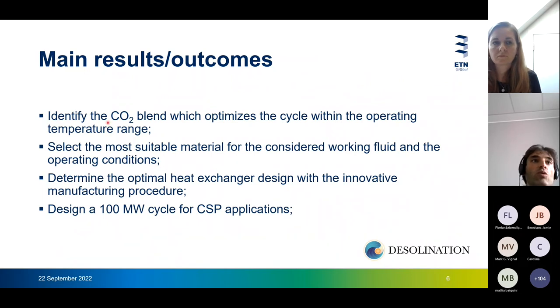The other outcomes which we expect in the upcoming years are to identify the CO2 blend which optimizes the cycle within the operating temperature range. One of the main differences from Scarabeus is that we work at a higher minimum temperature because of the coupling with the desalination part. Select the most suitable material for the considered working fluid and operating conditions. David showed that thermal stability of the fluid is relevant, but also the compatibility with typical materials for CO2. In our experience, sometimes blends are more aggressive, so the adoption of more expensive material is necessary, and a compromise between the two is mandatory.